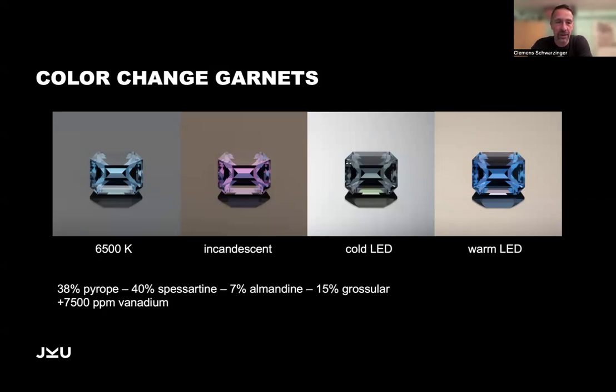at least in Arizona. We did analysis of this stone and it turned out to be 38% pyrope, 40% spessartine, a little bit of almandine, and a little bit of grossular, plus 7,500 ppm vanadium. That means parts per million, or in other words, 0.75% per weight of this material is vanadium. And this vanadium has an absorption band that is in the middle of the visible light. And depending on if your light comes in from the left or the right side of the energy spectrum, you can get one or the other color, the blue or the red, more or less.